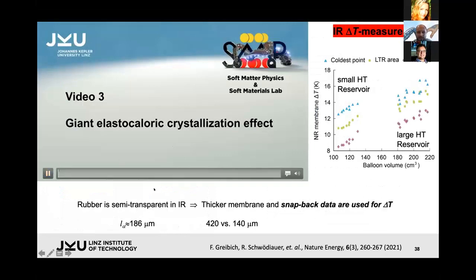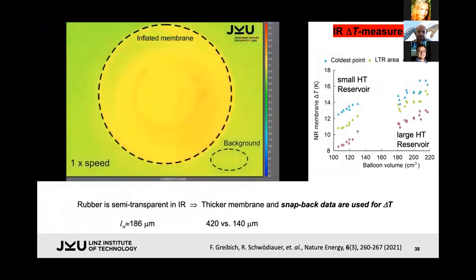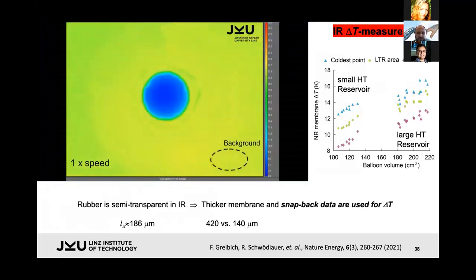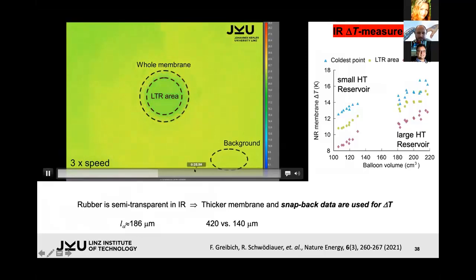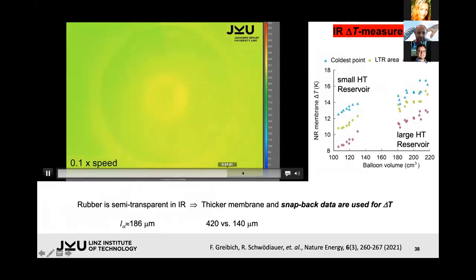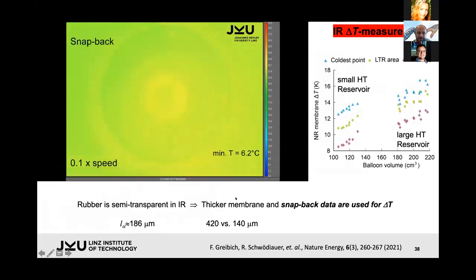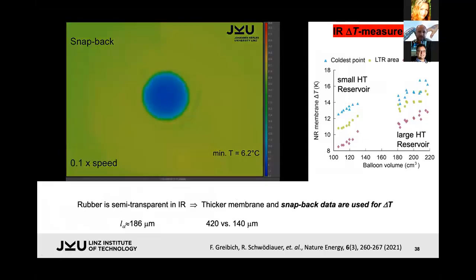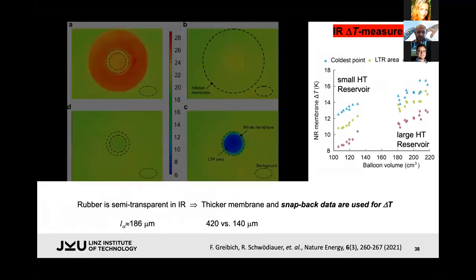So you can cool this rubber membrane with one snap-through. It takes place in a couple microseconds, actually by almost 30 degrees. You can harvest this change in temperature, obviously, to drive a heat pump. And if you extrapolate this, then eventually you can make a refrigerator out of such kind of a device. I would just like to show you that at the snapback, it's really, really fast. And the central part of the membrane here gets deep blue, which means that it gets very cold.